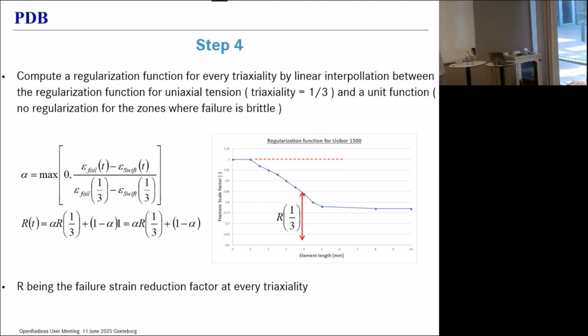And then we interpolate between the regularization function at a triaxiality of 1/3, which is the blue curve, and a unit curve, which is no regularization at all, which is what we do to the left of the intersection point, and that is just a horizontal unit function. Doing that, we get a regularization function for every triaxiality.